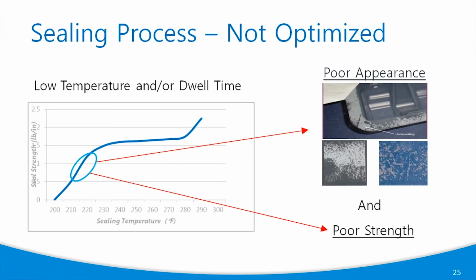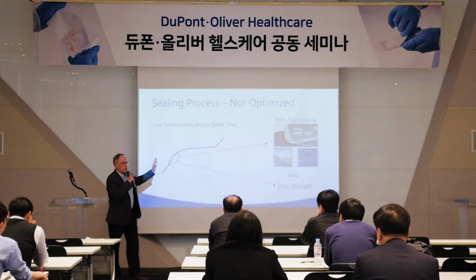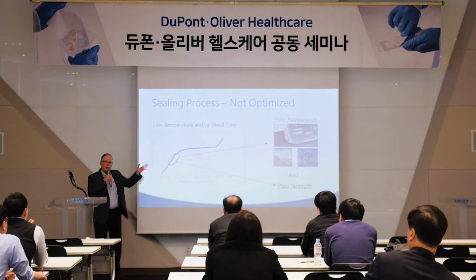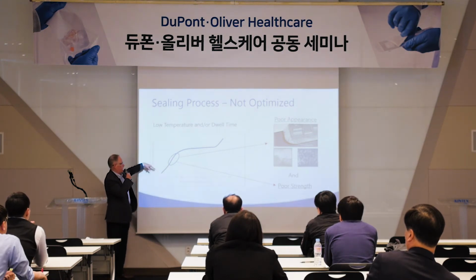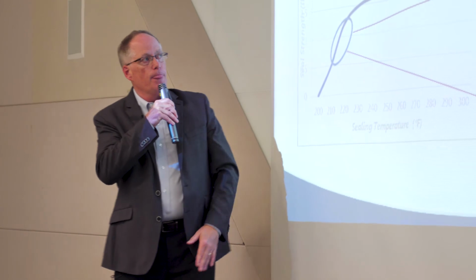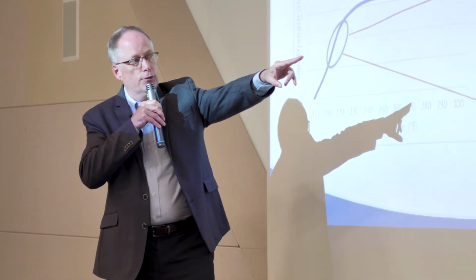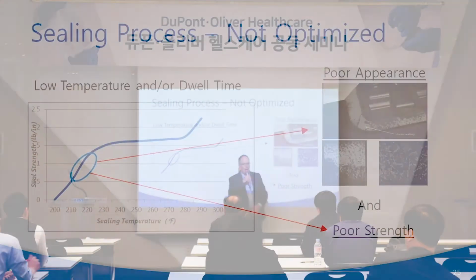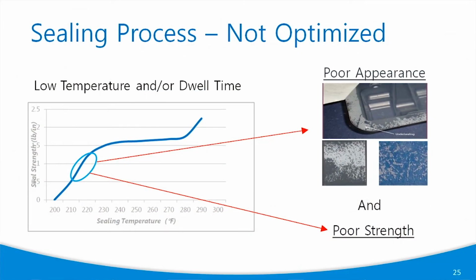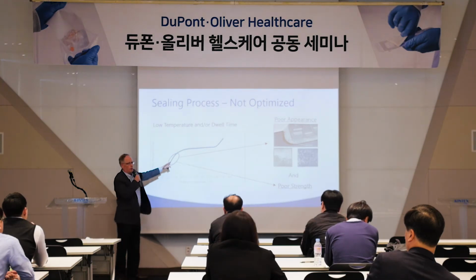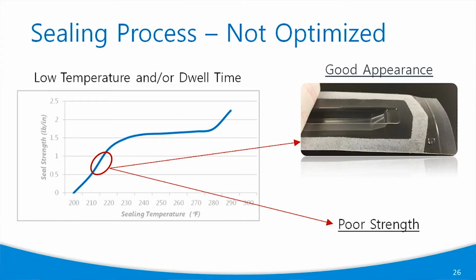So now let's talk about how to optimize your sealing process. So you're working on your equipment, you've got two materials you're now asked to qualify. It's a process to go through. This is one example where your sealing process is not optimized, and it's usually pretty obvious. So this is a seal curve again, where you've got an output of seal strength. This is your sealing temperature. In this type of scenario, we've got adhesive transfer that's not continuous. It's splotchy, it's not a complete looking seal, so you know you don't have enough temperature or dwell time as a part of your process, and it's obvious visually, and it's obvious because your peel strength values are low.